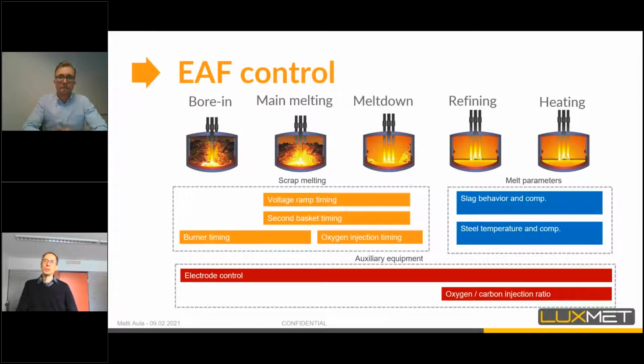So let's start from the electric arc furnace process. As we all know, it's a process to melt the scrap, basically. We want to melt the scrap and generate a melt which has the optimum temperature and composition. If you think about what we can control in the electric furnace, many of the parameters are related to the scrap and its melting. In the early part of the EAF process, the electrodes bore into the scrap, and when the electrodes are inside the scrap pile, we can input the maximum amount of power because all the scrap is shrouded in the arc and the sides are covered by the scrap. So most of the energy inserted in the furnace will stay with the steel.